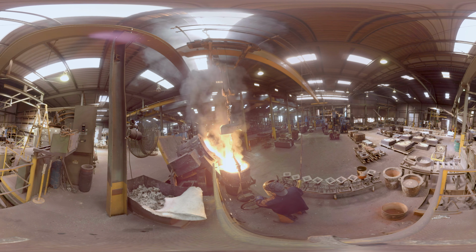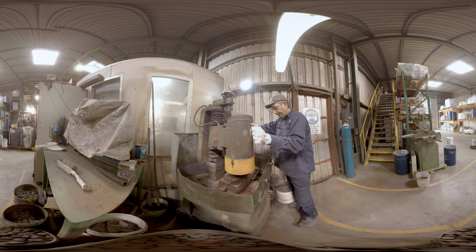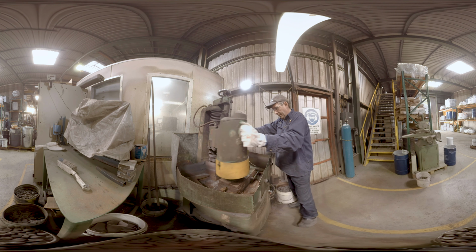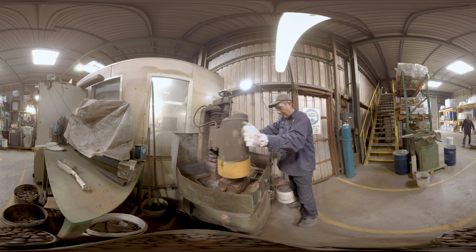All melts have charges calculated from various ingredients to make the right grade of metal for each casting. Every melt is analysed on one of 2 optical emission spectrometers. The chemical composition is measured by rapidly solidifying a small sample and sparking it on the spectrometer. Elements measured include carbon, silicon, manganese, sulphur, phosphorus, nickel and chromium, to name but a few. The result is compared against the specification. If it is in spec, the metal is tapped out for pouring. If it is not in spec, additions are made and the melt retested before pouring.